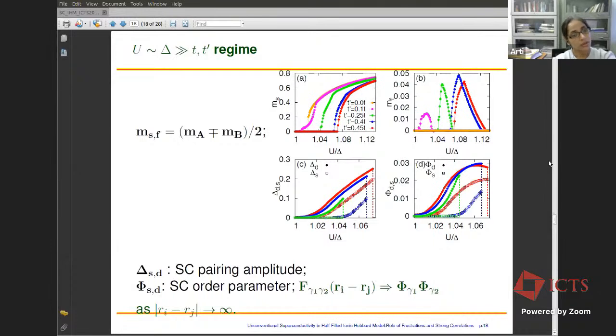This is a clear indication of the fact that the next-neighbor hopping is providing frustration against the magnetic order, because if you remember, along with the nearest neighbor spin exchange term, we also have a next neighbor spin exchange term in the model. And this frustration of the magnetic order and shifting of the critical point as you increase the strength of the next neighbor hopping actually helps in stabilizing the superconducting phase. Another interesting feature is that the uniform magnetization also turns on for a larger range of U by delta. It means that the system won't have only an antiferromagnetic order, but there is also a range of U by delta for which we see the ferrimagnetic order.